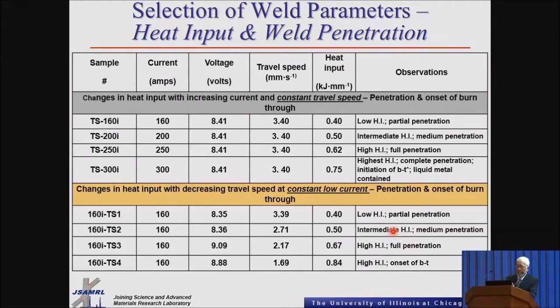So in our first part, what we wanted to do is change the parameters, more current as well as travel speed. If you take a look at this table, it looks very confusing, but let me drive you through this table. At first we held the travel speed constant. All we did was change the current. You can see the current 160, 200, 250, and 300 amps.